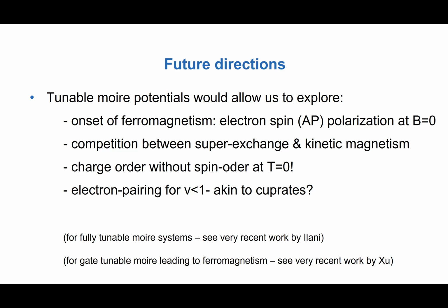Yes, so basically this is one of the things that we do not understand. What I would say is that if you look at Allan MacDonald's calculations for the parameter regimes that we are dealing with, the direct exchange should dominate over superexchange. I told you a kind of historical story that we were expecting superexchange to be dominant, but for these parameter regimes, he calculates that the direct exchange is the dominant term. So the answer to your question is that if it was really a direct exchange effect, I do not see why nu equals one should not show ferromagnetism. What Allan analyzed is nu equals one, the Mott state in the triangular lattice, and he's saying that for such interaction length scales and for the potentials that we have, one should have a ferromagnetic ground state at nu equals one.